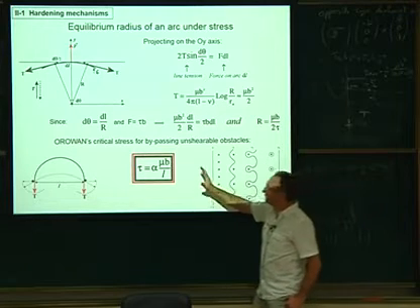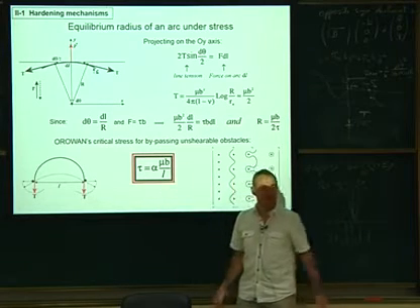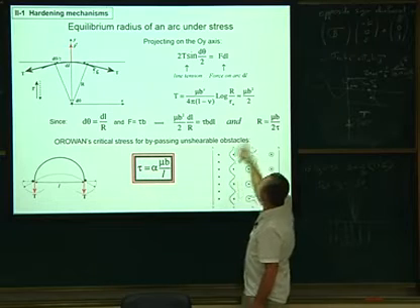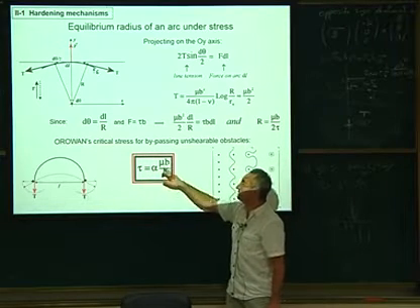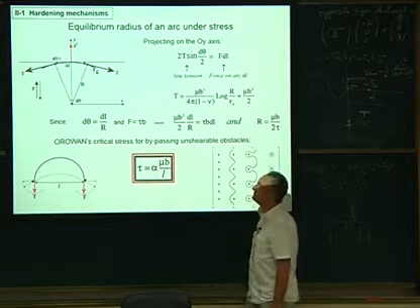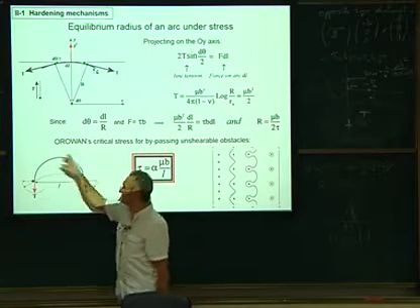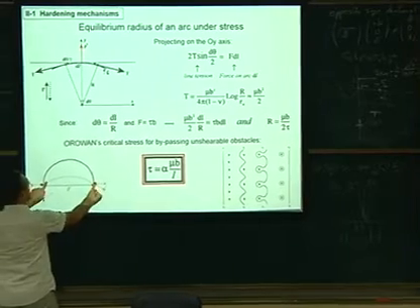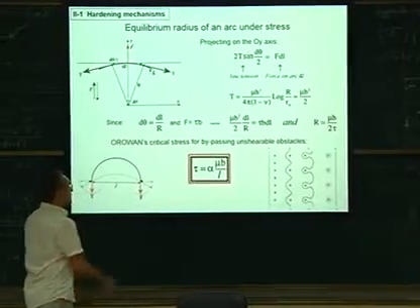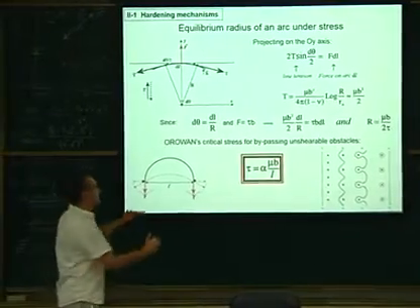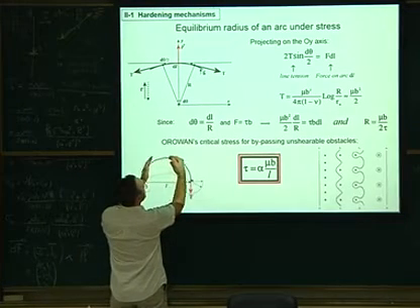This one, I put many lines out of it because this is very important. So the stress now is alpha, so it's the inverse of this, alpha mu b divided by the length of your curved arc. So typically, if you have a Frank-Read source like this, a dislocation segment which is pinned like this, the critical length for this segment to be active will be when the curvature is maximum.